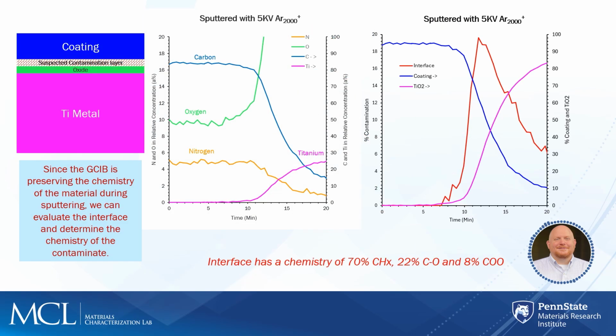So now we're going to have a more practical look at what the GCIB can do for us in terms of this example. So again, we've got this coating with an interfacial material, or suspected interfacial material, on an oxide on a titanium metal substrate. And we think that there might be this contaminant layer, and we want to know for certain if there is. With the monatomic gun, we couldn't do that.